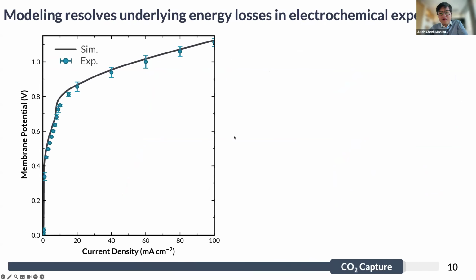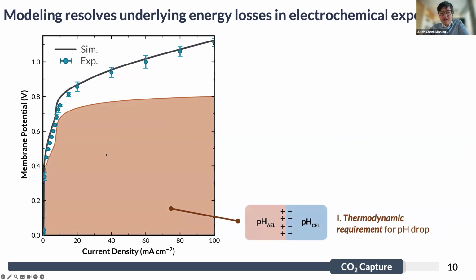The other thing we can do is we are really interested in the energy efficiency of these systems. And so what we can do is resolve the contributions to the applied voltage. So not just the contributions to the current density, contributions to the voltage. We can see that there's a lot of voltage or energy that's being put into this membrane to drive the system that is just purely thermodynamic. So it's unavoidable. If you're going to try to create a pH gradient across the system, there is a price that you have to pay to create that pH gradient.